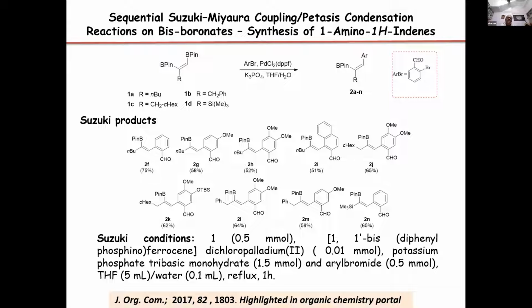So in this direction, what we have done is we have subjected the bisboronates to Suzuki reaction with aryl bromides having a formyl group in them. So we have used the 2-bromoaldehydes, substituted 2-bromoaldehydes in the Suzuki coupling reactions, and we made a variety of Suzuki products having a formyl group in these systems in 50 to 75% yields under standard conditions. Then having prepared the substrates for the intramolecular Petasis reaction. Next, please.